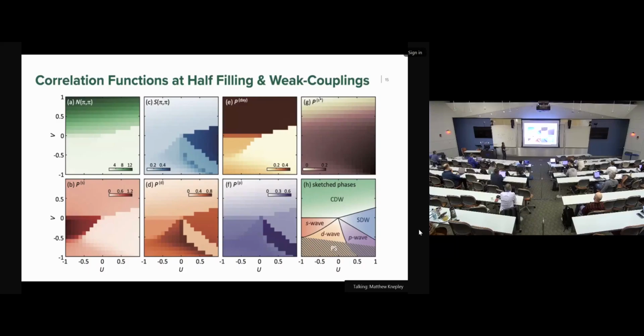From this we try to extract a phase diagram of U versus V for different possible phases. This region, called phase separation, means that the particles become hole-rich and hole-deficient regions, so they are irrelevant for our calculation. So we focus on this region.